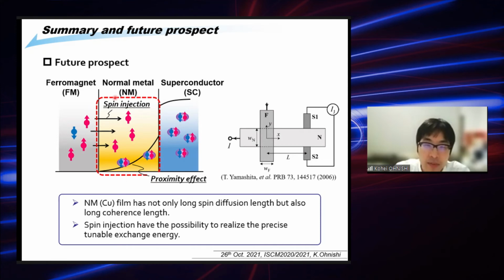And also the pure spin splitting in this normal metal layer can be easily tuned precisely by the spin injection, by the non-local spin injection. So this normal metal layer can be a good platform to explore the interaction of the spin polarization and the Cooper pairs.